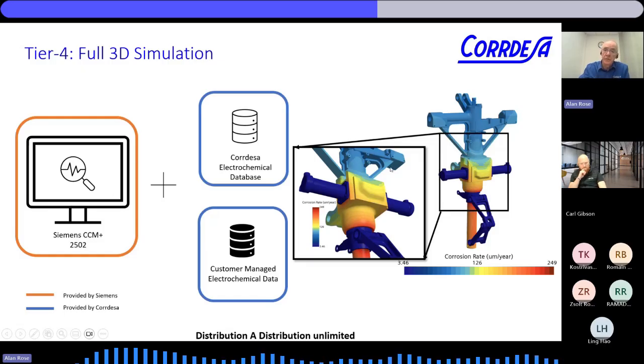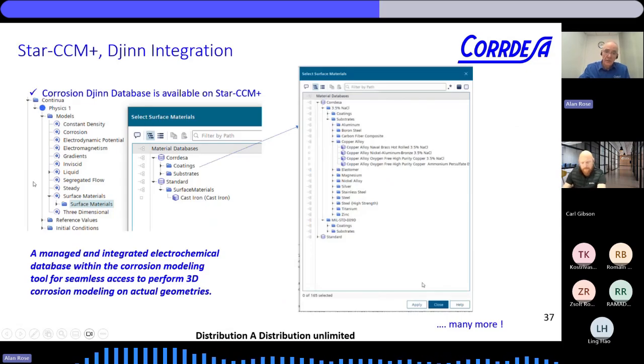So we're using computational fluid dynamics, but we also solve now for corrosion rate. So we can read in our database all those polarization curves, and it's available actually within the software, so you can set up your design tree. We have surface materials here, and here you can see that Corrdesa database with the coatings and substrates all available just to be quickly assigned to those surfaces of the geometry that you're considering.